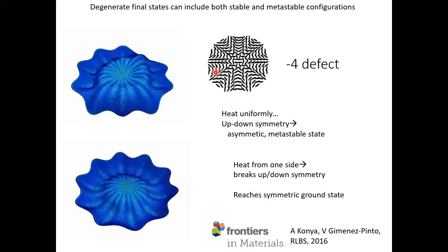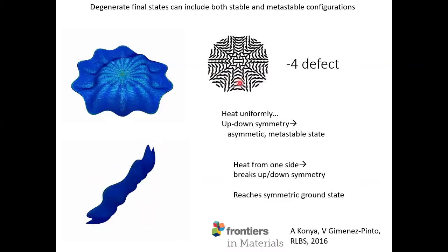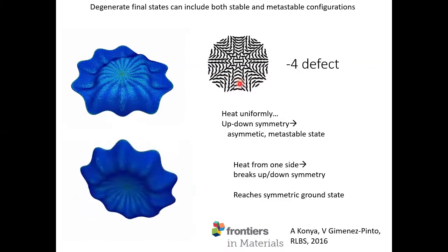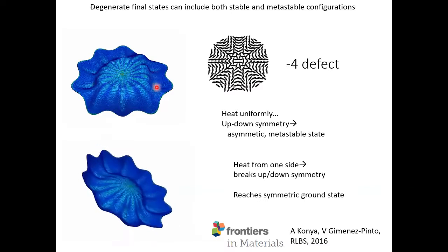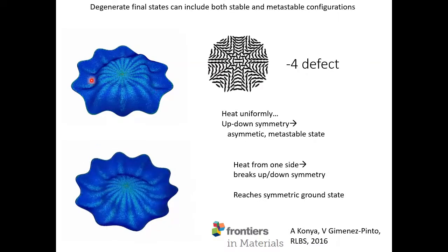And when you heat something like that, there's nothing that breaks the symmetry between the front and the back. And so in principle, each little section of it can pop forward or pop backwards, and you get a rather disordered looking structure. The experiments were done with the heat always coming from one side. So we tried to model that, and we modeled the system so that if we always heat from the top, so there's the thermal gradient, the top is hotter than the bottom, the scalar order parameter is lower on the top and higher on the bottom, then lo and behold, the system always pops one way, and you get this very attractive thing that looks like a candy dish.